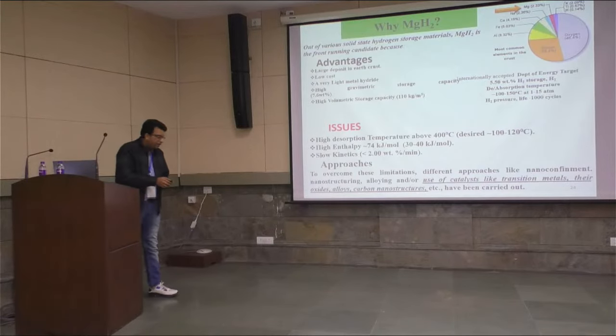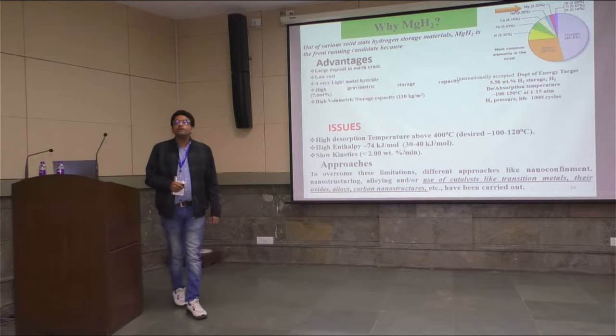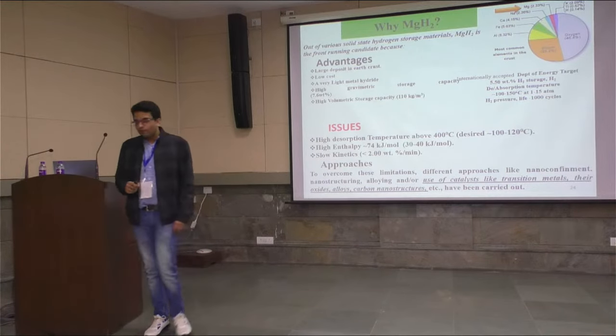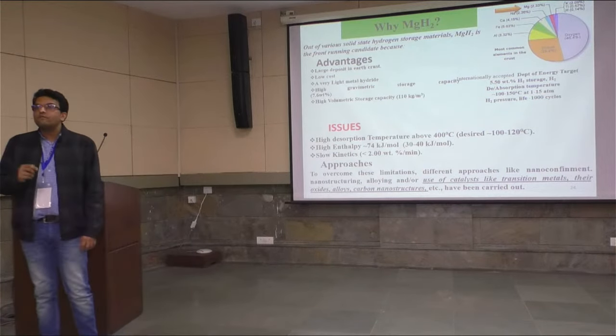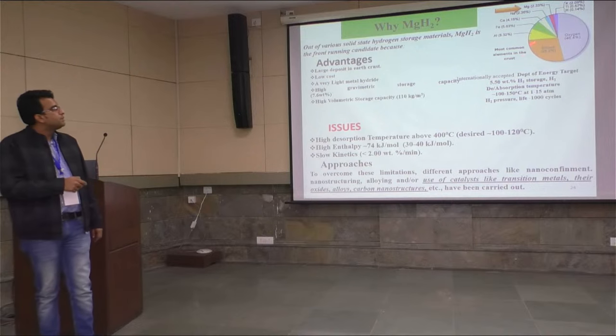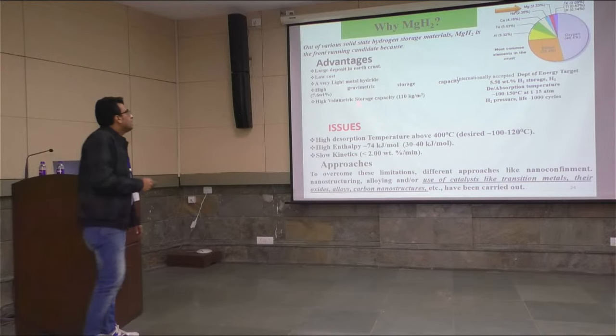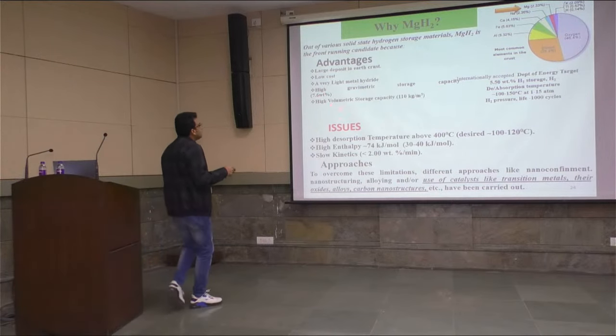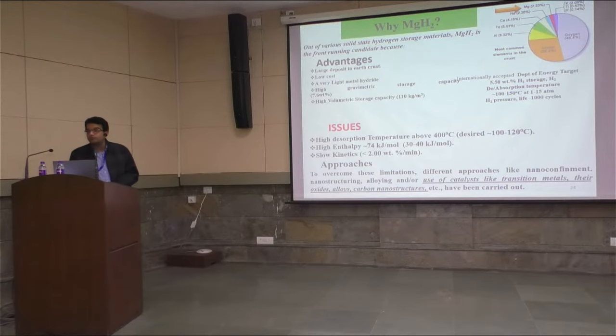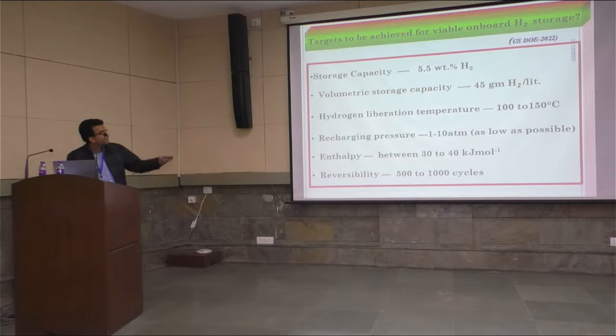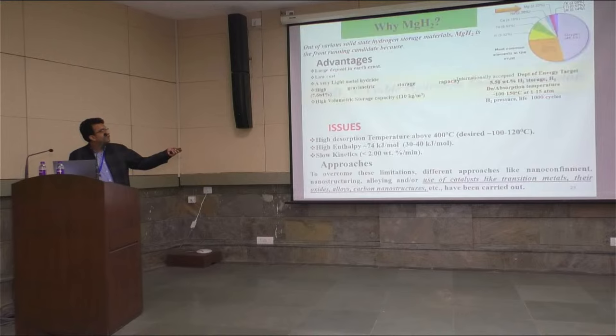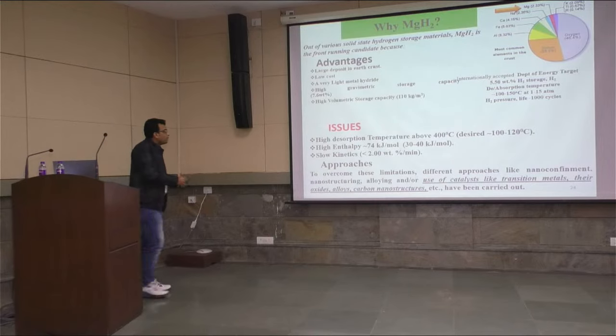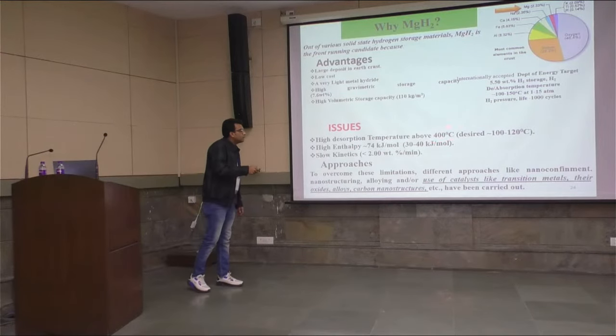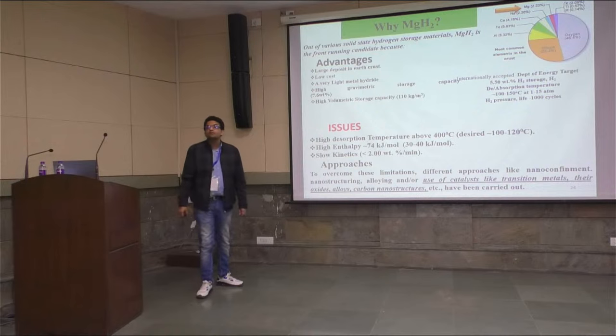Why magnesium hydride? If you want to use a material, the first thing we can think about is the availability of that material. So magnesium is the 8th most abundant element, and it has a storage capacity of 7.68%. So naturally, you store 7.68% hydrogen, and the target is 5.5. So it is way above the target. But the problem is that it has a high desorption temperature, 400 degrees Celsius.